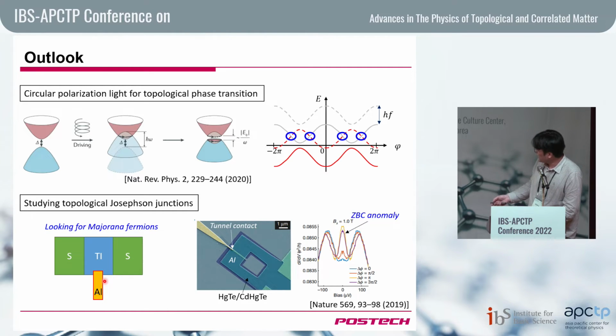Interestingly, Amir Yacoby's group at Harvard made a similar structure. Here they use a mercury telluride, cadmium mercury telluride heterostructure, which is basically a 2D topological insulator, and made it into a Josephson junction and put on a side tunneling contact. By applying the right amount of magnetic field, they were able to see the zero bias anomaly, which is the signature of the Majorana state. Yeah, and that indeed is a very interesting and related structure.